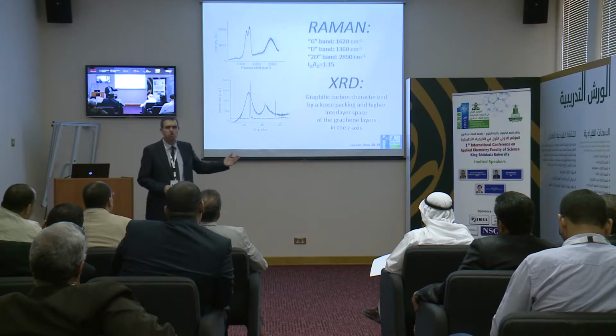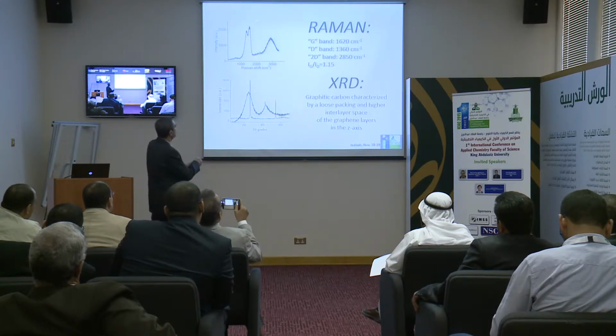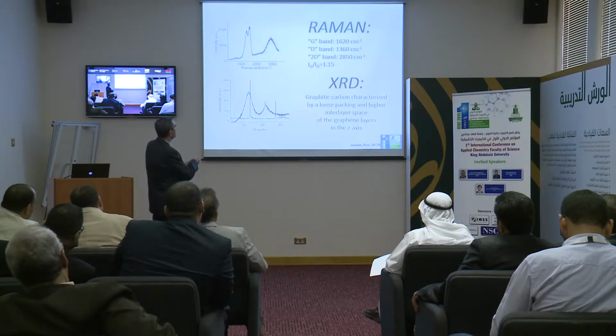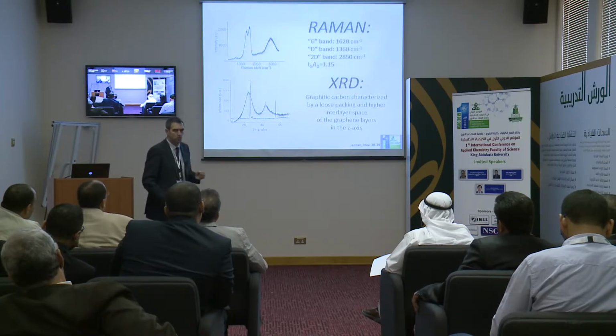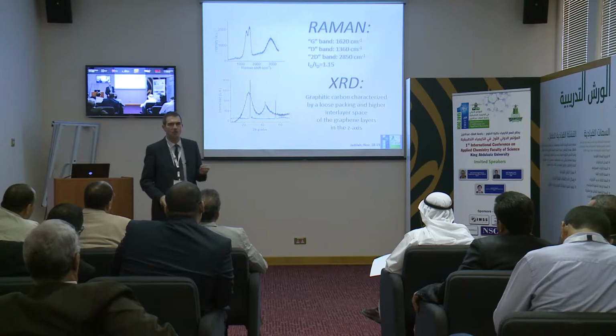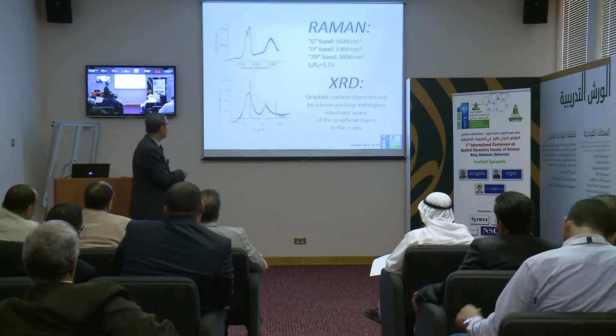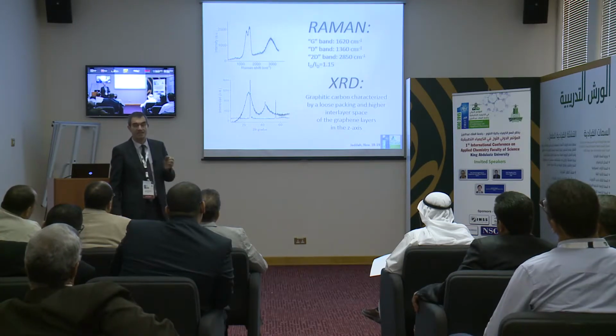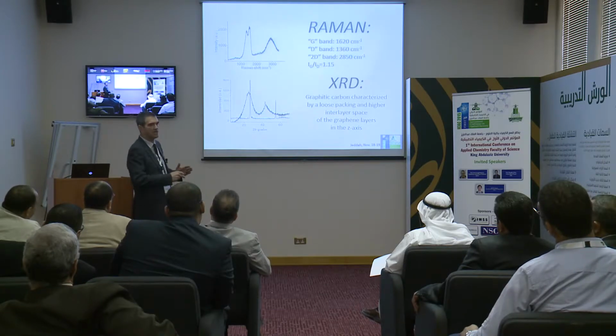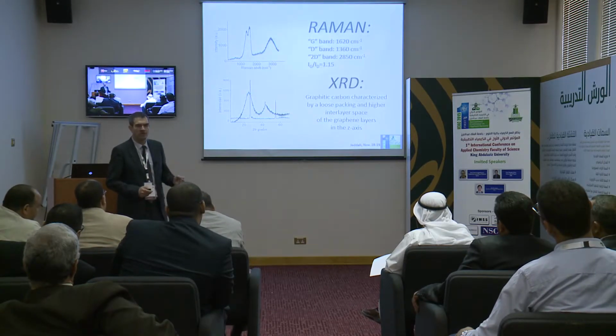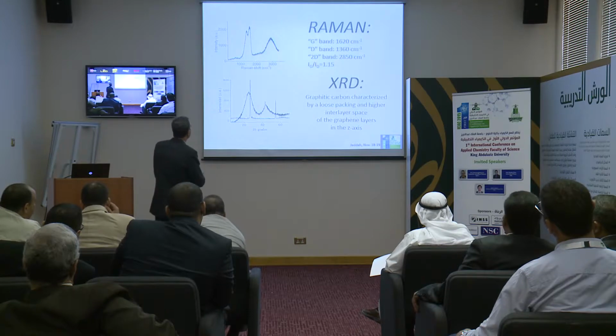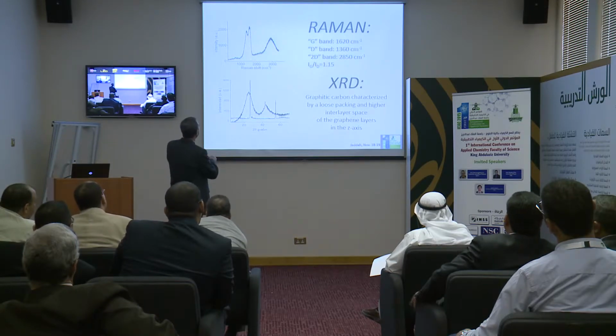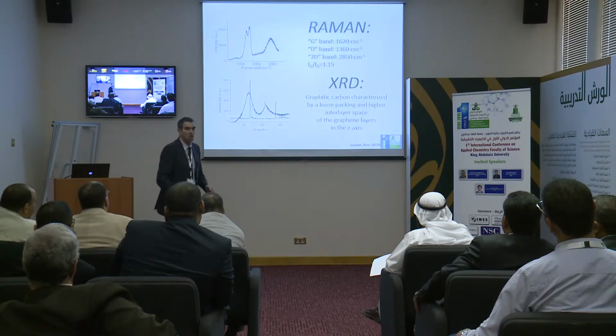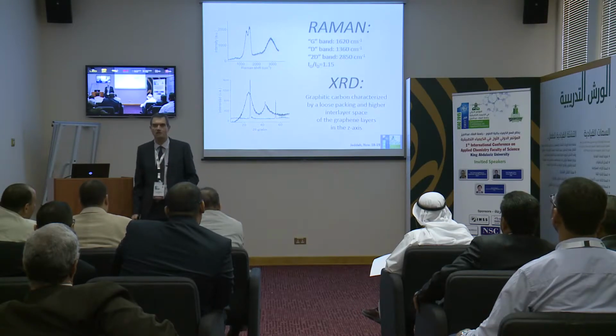Besides electron microscopy, we also have to do spectroscopy, and this is the typical signature of a graphene with the 2D band. This 2D band is usually used to know how many layers we have. If this 2D band is very sharp, then we have single layer graphene. If it is a little bit broader, then we have few-layer or multi-layer graphene. And this is the graphitic band, and then we have another band here that is related to defects, to sp3 carbons.